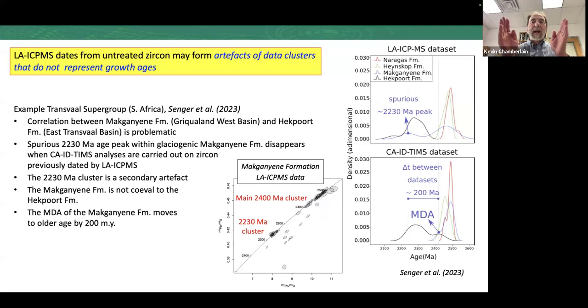simply annealing and chemical abrasion, and the other thing that's really impressive about the annealing is that it changes it from a Gaussian normal distribution to more of a skewed one. It removes that population that are too old, and so it brings it down. The only factor you have left then is lead loss, and it even shortens that effect. These were on zircons that had been dated by both methods that he'd pulled out of the literature.